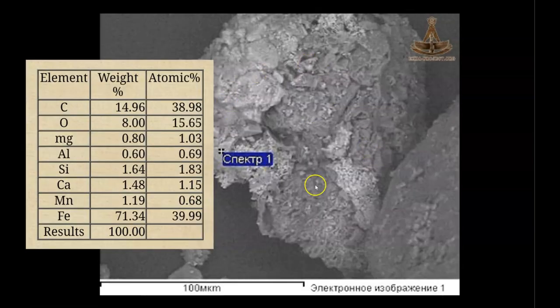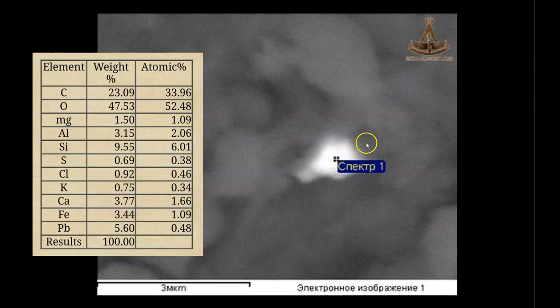Here is some iron oxide crust on a grain of sand, 71% iron. And here is a grain of galena, lead sulfide, which I discussed in the previous episode, is a very prominent and typical ore mineral found all across Egypt, 5.6% lead, 9.55% silicon, and the rest is the background matrix.